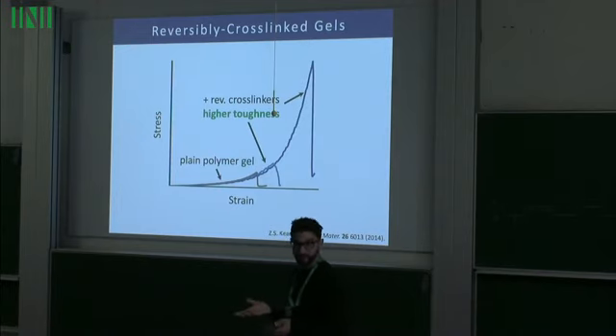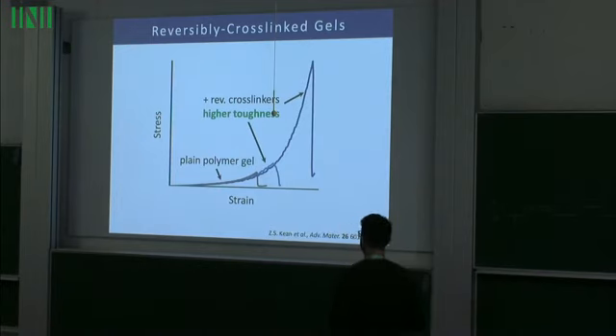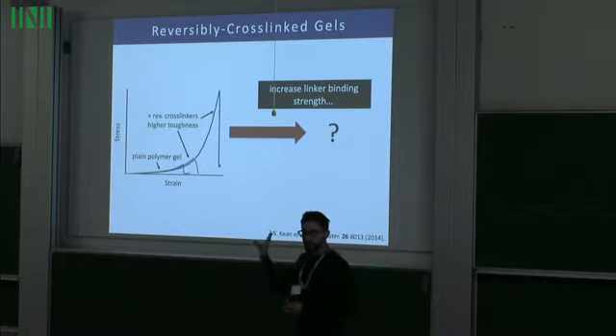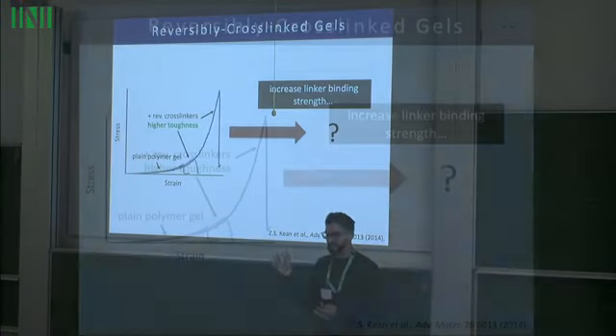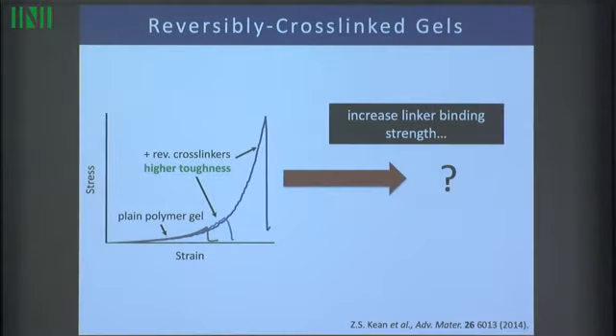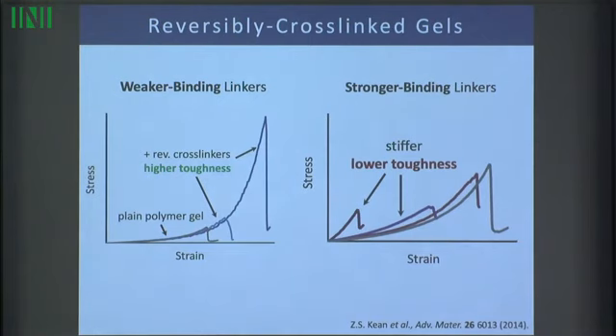And this is very interesting from a theoretical perspective. Okay. That was for one choice of reversible cross-links. You can choose other structures for these reversible linkers. And in particular, if I increase the binding strength, I get quite a different behavior. I get this behavior shown here.